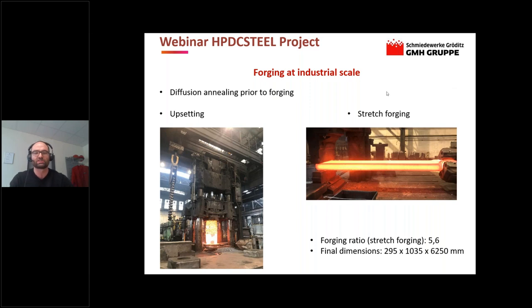Looking only at the stretch forging process, we were able to obtain a forging ratio of 5.6 for this forged tool steel bar with a rectangular or square section. This high forging ratio is the key to closing 100% of the porosities which possibly came from the former ESR ingot. Additionally, it is the key to producing a very fine-grained and homogeneous microstructure by recrystallization during the forging. And finally, by forming in all three dimensions, we obtain a hot work tool steel with nearly isotropic properties.